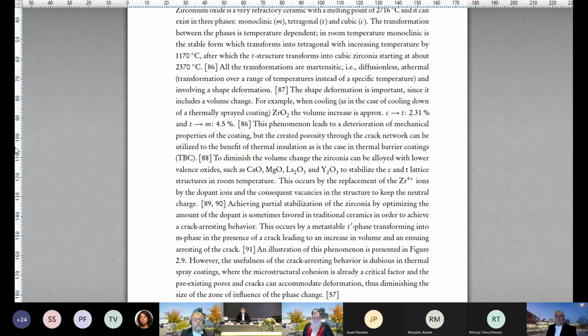There's something to look forward to if we could create dense enough coatings, possibly. But for now, as I mentioned in the lecture, there are pores and cracks and voids, discontinuities inside the coating that have a larger effect. So this crack arresting I can't see, and I've tested it with various methods. I didn't find an effect of this, and probably it's because the crack won't be arrested if it has a pre-cracked route to go around, or a pore to enter, or the lowest resistance of propagation.